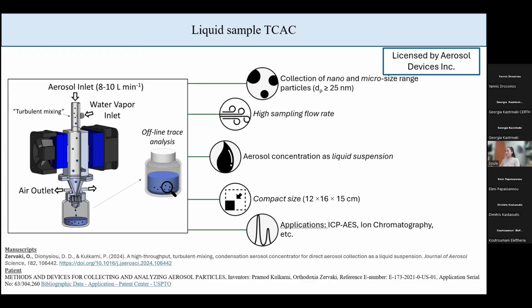the growth efficiency of the droplets. After the growth tube, we have the converging nozzle that again concentrates the droplets into a small beam, which then impacts on an inclined surface, sliding on it, and then there was a hole at the bottom of the surface where the droplets were flowing through, concentrating at the bottom of this collection vial, which at the end of the